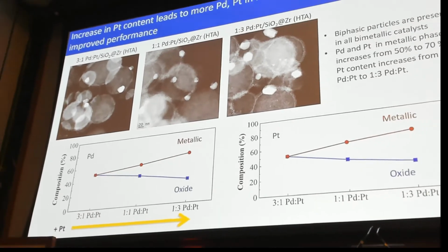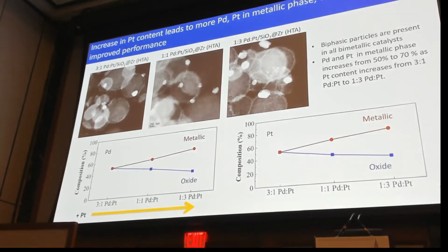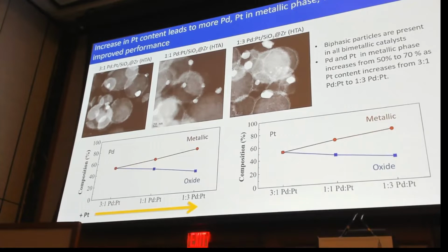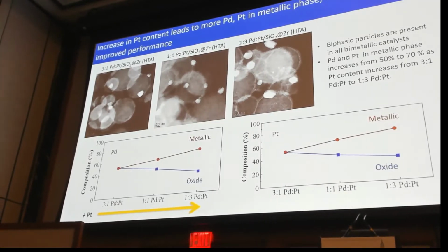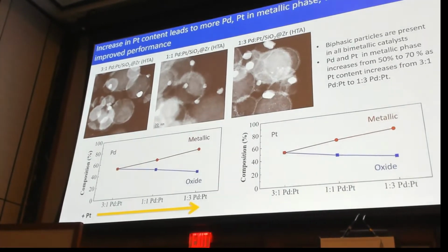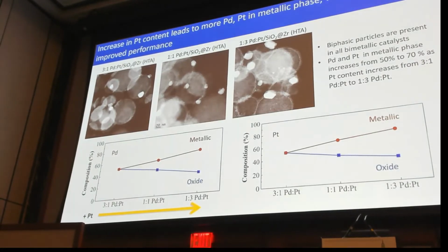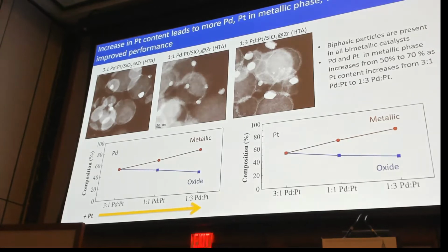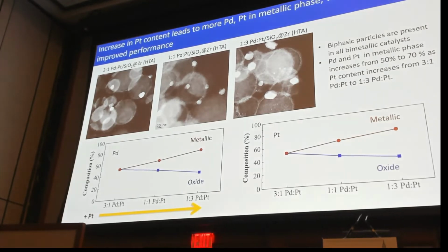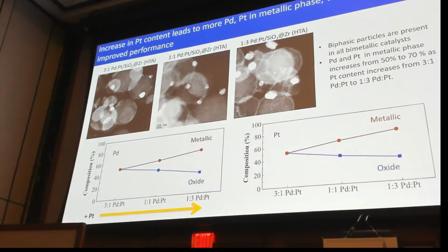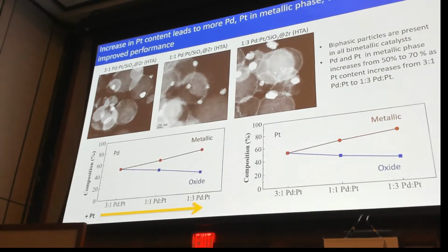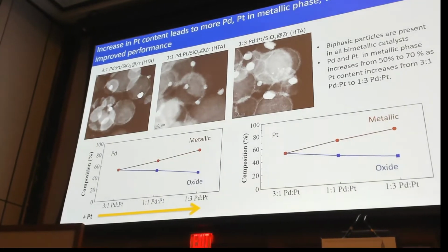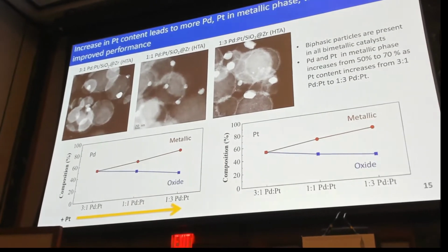So again, Dr. Barker and his team did an analysis of these biphasic particles, and here we summarize the results. So the left figure shows the palladium composition over the three bimetallic catalysts that we have. Again, from left to right, we increase the platinum content. So what we see here is that in the biphasic particle, 70% of palladium is present in the metallic phase, and 30% of palladium is present in the oxide phase.